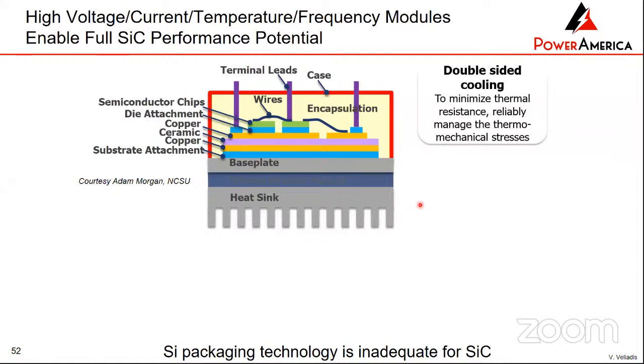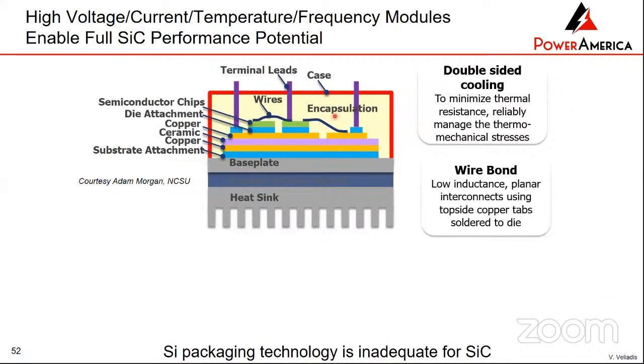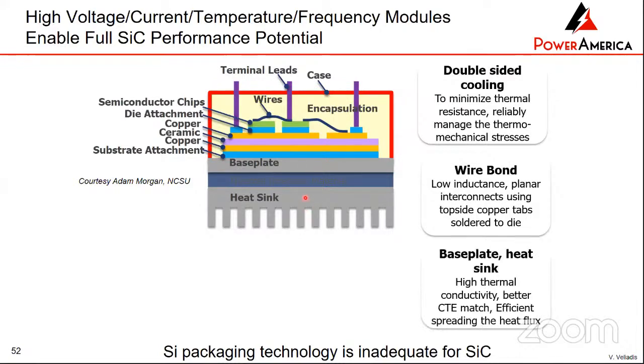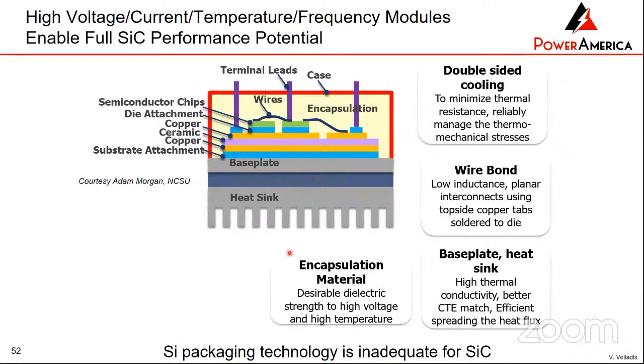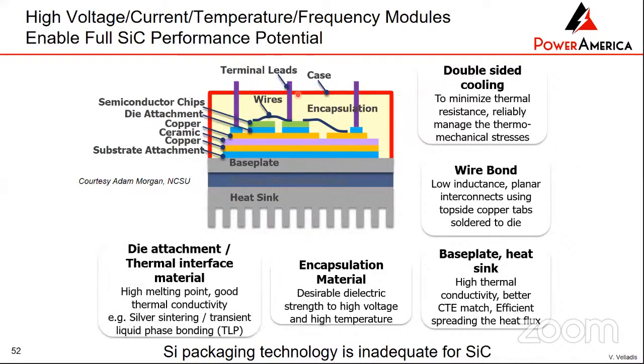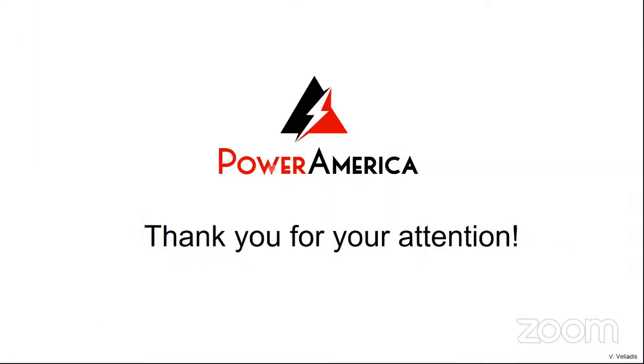There's a lot of developments and a lot of innovative work happening in modules. You want double-sided cooling. You want to be able to cool from the bottom and the top in order to extract the heat. If you're going to use wire bonds like here, they have to be very short. And it's a good idea to get rid of wire bonds altogether and use tabs, because wire bonds introduce inductance, and when you operate at high frequencies, inductance is a huge problem. You want to do innovations in the heat sink and base plate to extract the heat. You want to encapsulate the device with some sort of gel that will handle both high voltage and high temperature. You want to make innovations in die attachment and calculate all the thermal interfaces.